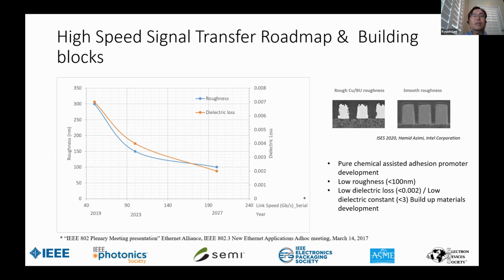we are targeting that the dielectric loss should be less than 0.002. And the dielectric constant is not really critical in this HPC, but we target that it should be less than 3. We also found out that roughness is starting to play a role. Not the copper roughness, the dielectric material roughness after desmear also needs to be lower.